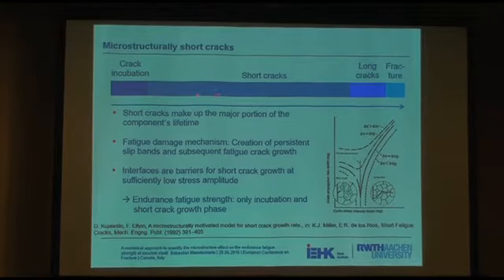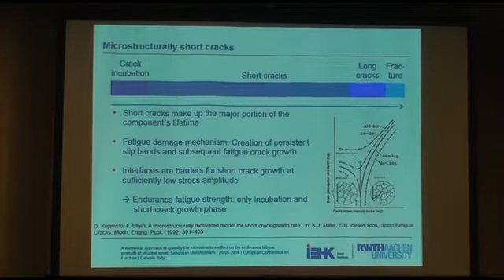Then we will have a very long period where mainly short cracks are growing due to the cyclic loads. And of course, this somehow depends also on the applied stress level. There is a somewhat shorter period where we've got the long crack growth, and finally a very short term, which is the final fracture. In fact, this is almost zero of the lifetime, but then you wouldn't be able to read the word fracture. So I reserved some significant space for this.